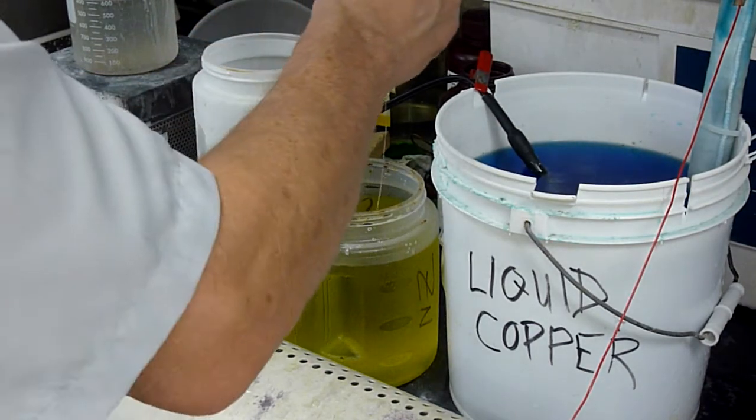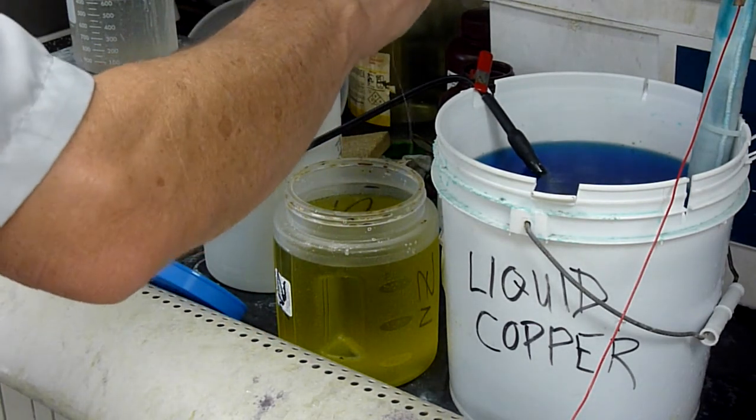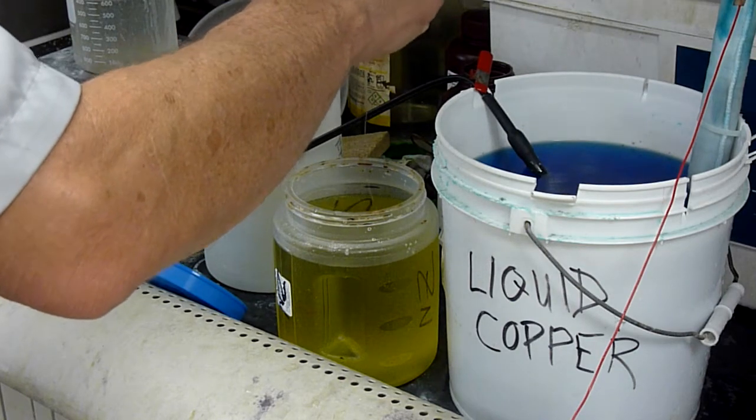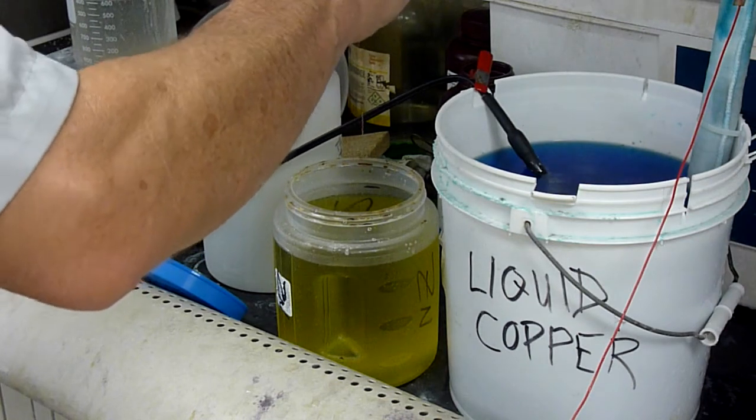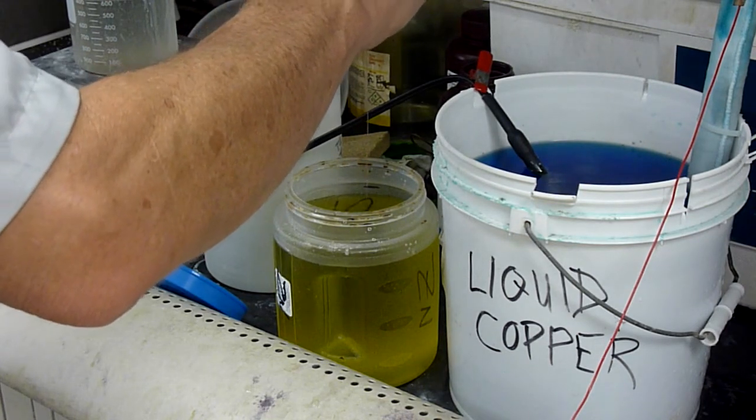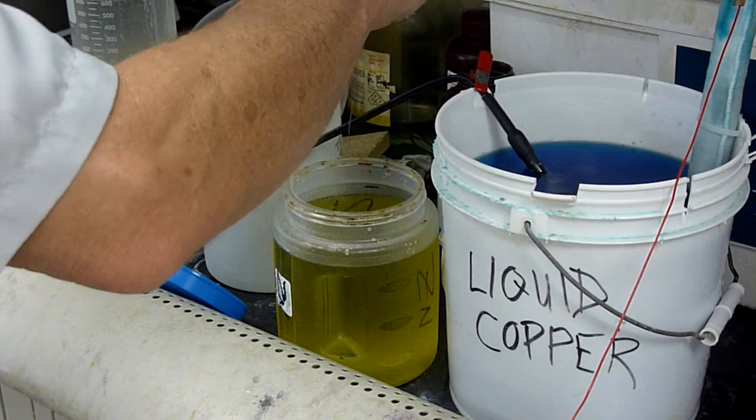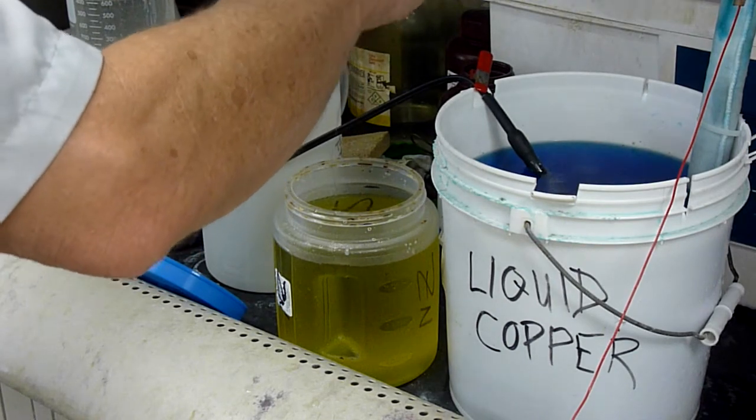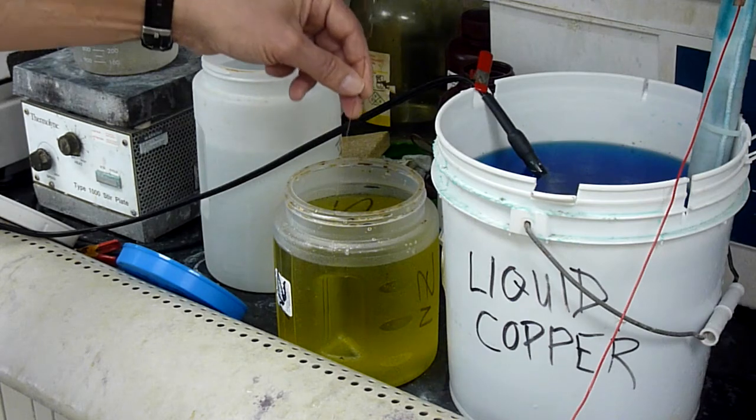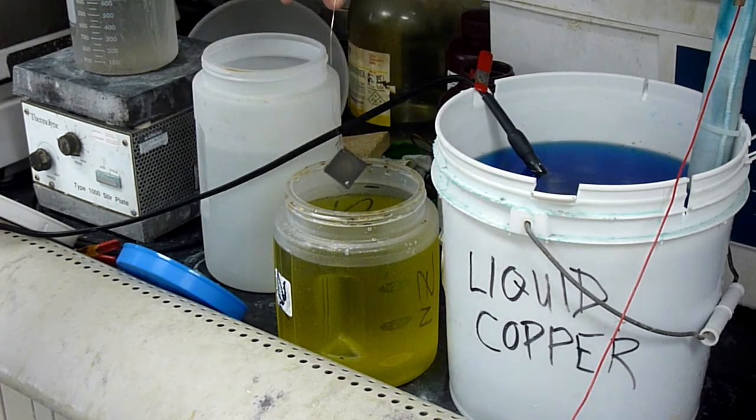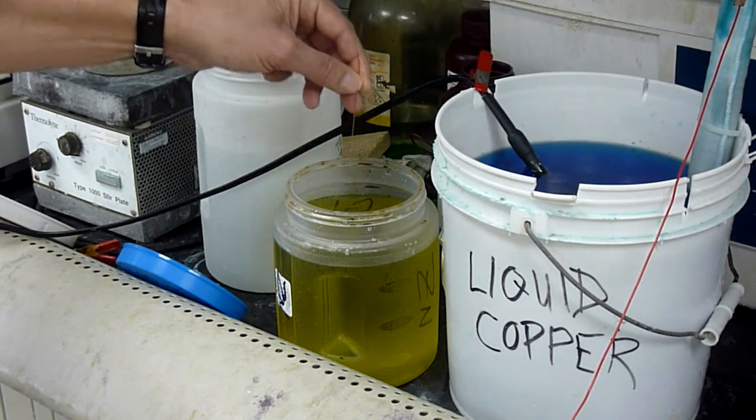Again, the time is not critical, but give it typically 20 to 30 seconds. It can even go a minute. There's no reason to not go longer. And you'll almost always notice that on the second zincation step, you get a different coloration than on the first. And for some reason, it's not necessarily uniform. In this case, I'm getting a darker coating, I would say.